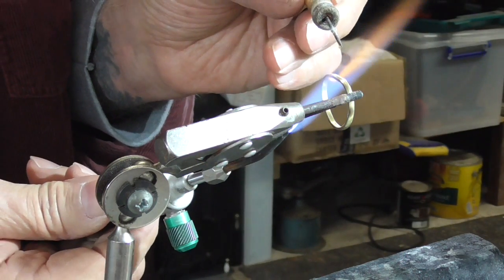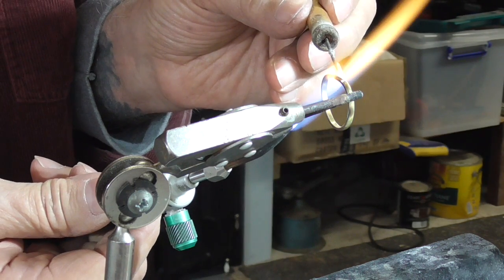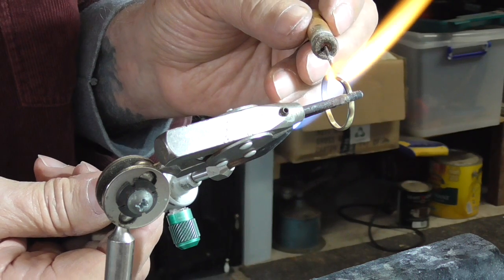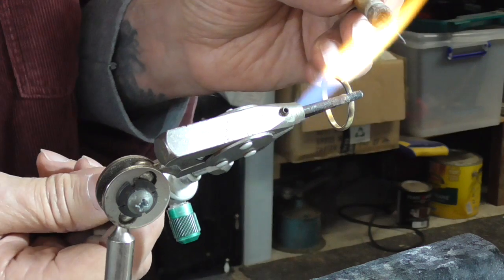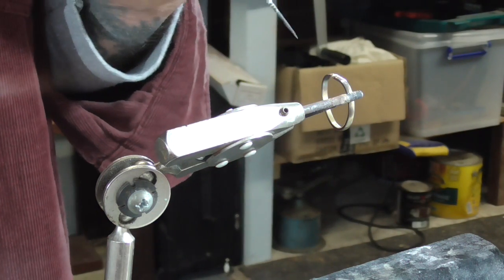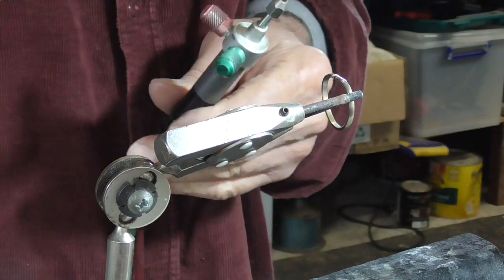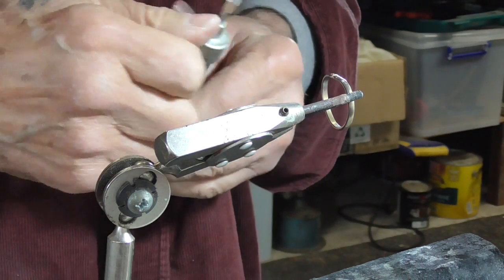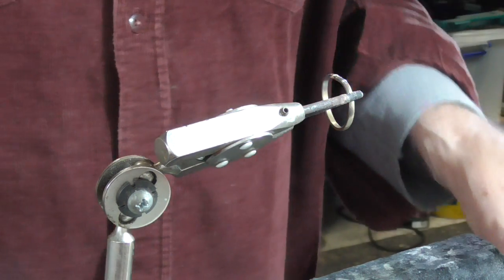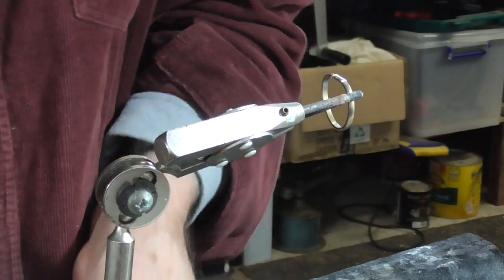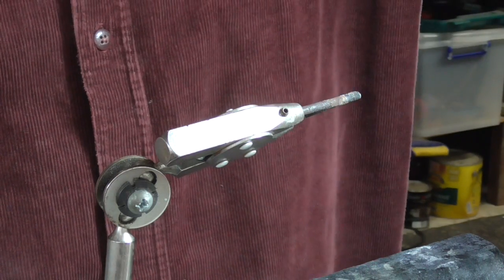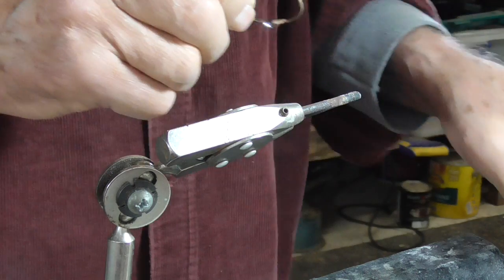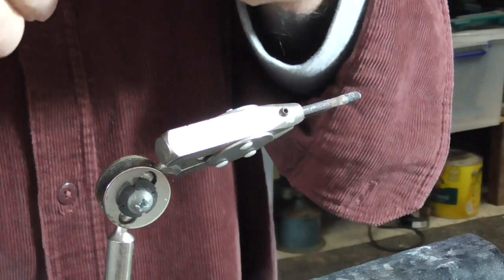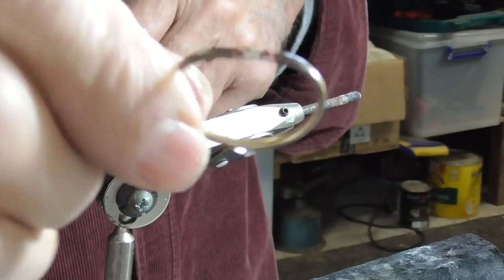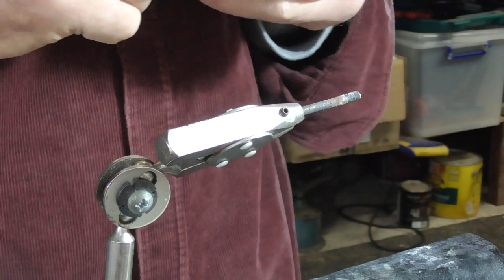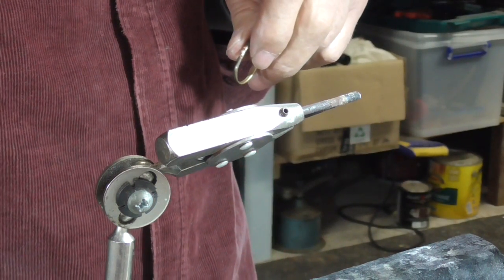And I'm going to heat from underneath. Place the solder on top. And when the solder flows, give it about a second and then take your flame away. If the solder doesn't go where you want and you try to shift it with the flame, you'll just melt the piece. So don't do that. You can push the solder around with your solder pick, but you don't have a lot of time to do that. It's usually easier to back away, use another little piece of solder, and place it on it. So you can see the solder flowed through, and there's just a little bit on top to clean up. So we'll pickle this and then tidy it up, and we're ready to assemble the ring.